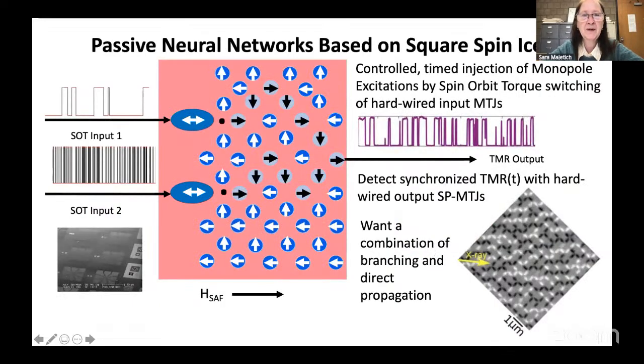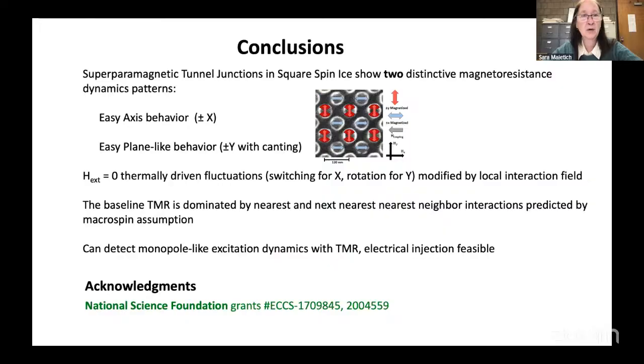What we want to do is to take our smaller, faster spin ice and do the same sort of things. Ideally, if you wanted to make a neural network, what you would do is to have independent inputs where you could inject, create type 3 nodes and let them diffuse. If you could inject them close together, you could look at their interactions, and we could do this with synchronized resistance measurements, which we've already done on independent tunnel junctions. So this is the future direction that we're looking at.